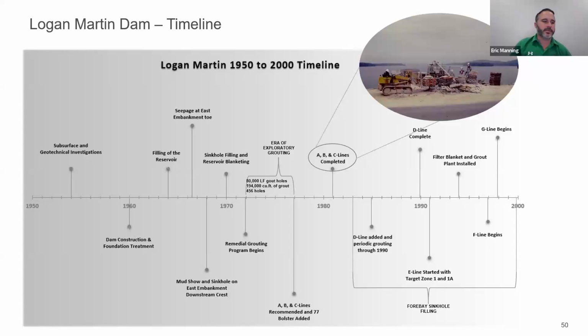But in later years, as those grouting programs progressed, we noticed that there were a lot of piezometric responses on relatively deep grouting, which led us to see that the permeability of the rock and its hydraulic conductivity connected relatively quickly and shallow, and to piezometers that were relatively close upstream. So this led to us extending the grout curtain much deeper to what we do now.